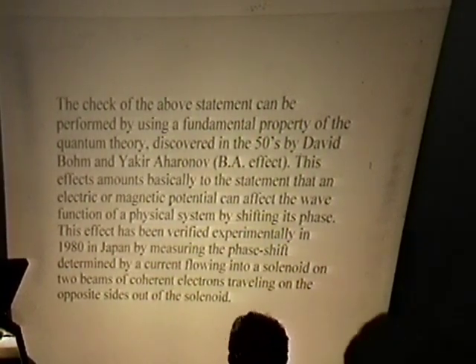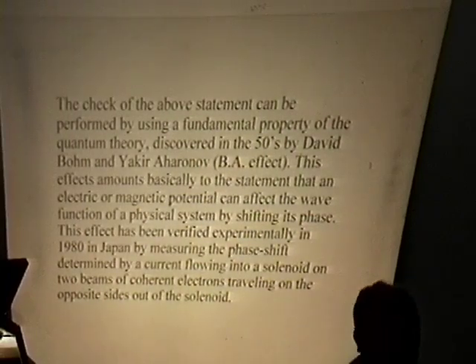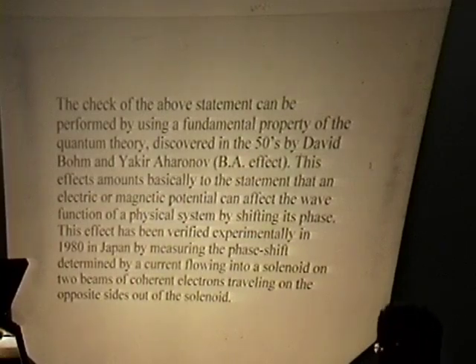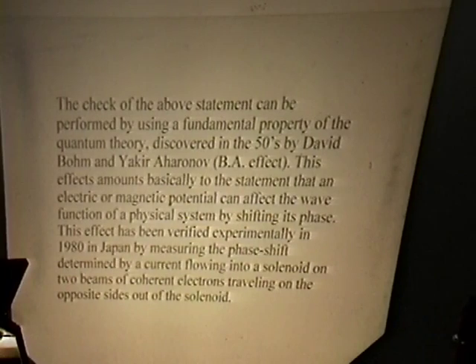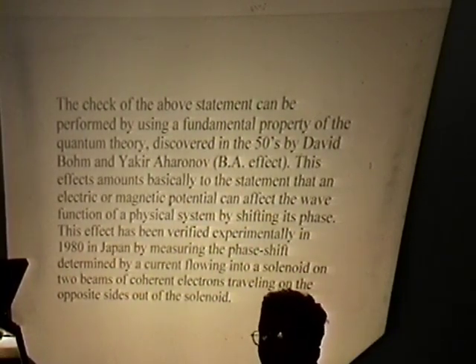Of course, when you have a piece of macroscopic matter, if this piece of macroscopic matter is described not by a unique wave function, but by a density matrix of wave functions, namely by a mixture of wave functions, each one referring to a single particle, but the relative phases of these different wave functions are uncertain, in that case the phase averages to zero, and this effect cannot be observed. But if you are able to fix the phases, and that occurs in a coherent state, you can observe a Bohm-Aharonov phenomenon. So the observation of a Bohm-Aharonov phenomenon will mean that the system you are observing is a coherent system. And this is the experimental proof of the existence of this coherence.